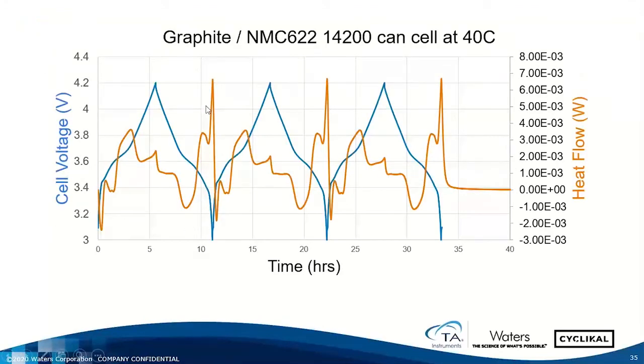All right, so what does the thermal power look like from a standard lithium-ion battery? So this is a graphite negative electrode with a nickel manganese cobalt 622 positive electrode. It's in a coin cell. I'm sorry, not a coin cell, but a 1/3 AA cylindrical cell, 14 millimeters in diameter and 20 millimeters long, and it's at 40 degrees C. The orange is the thermal signal from the battery, and the blue is the voltage signal.